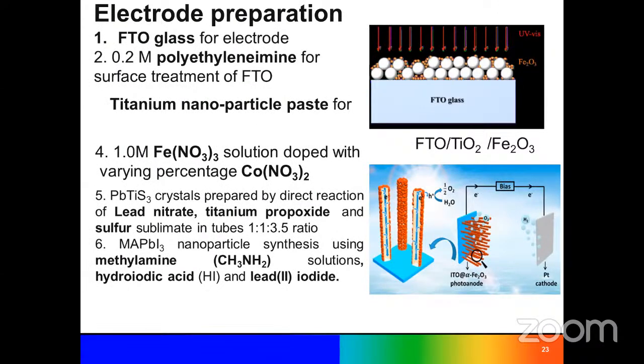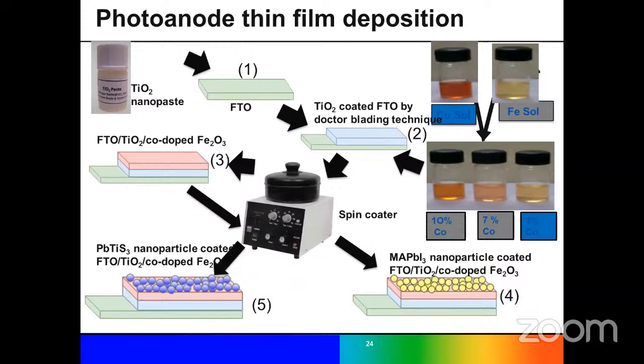So this is the process of how we fabricate this photoanode system from the FTO, fluorine doped tin oxide. We coated these materials on top of the TiO2 surface. Then hematite materials will be deposited. Then cobalt doped on hematite material, with different amounts of cobalt doping deposited, and finally we checked the electrical and optical properties. And this is the process we used, the spin coating process, where